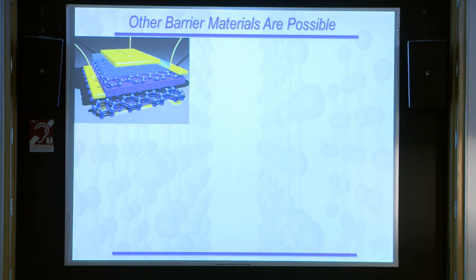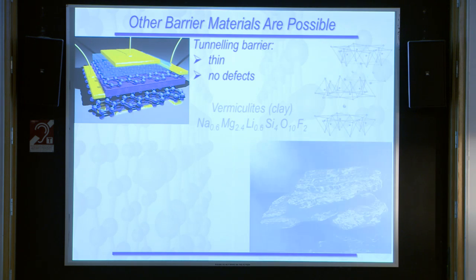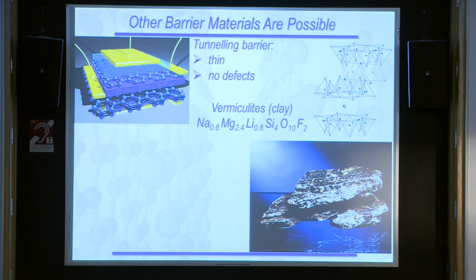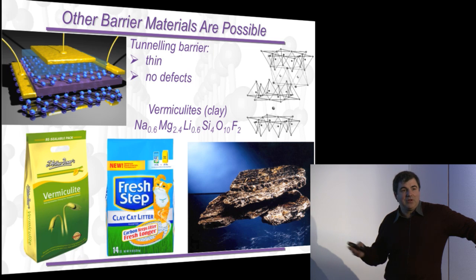Just to give you an example that the variety of the materials which we can use is quite large as well. We also produce so-called tunneling transistors made from very unconventional material. Traditionally, people use boron nitride, tungsten sulfide, but in principle, you're not limited by anything as long as it is reasonably high quality material, quite thin, can be exfoliated into monolayers, and there are no defects. And for example, we can use clay.